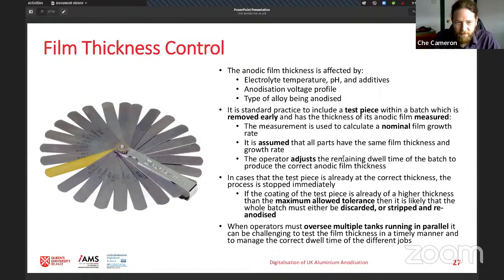There are a few issues with the assumptions there, that you're assuming the process is the same on all the different parts and all the different types of parts, but this is how it's generally done, and it's reasonably reliable. There are cases that when you remove that test piece, the anodization is already at the correct thickness, in which case you stop the process immediately. But it's also not uncommon that you remove that piece and you see that the film is too thick already for a geometrically accurate part that may be beyond tolerance now. So you either end up discarding the whole batch or you strip and re-anodize it if that is feasible for the part. And the reason that this can be an issue is an operator may be overseeing multiple tanks running different type of parts at the same time, and it can be hard for them to get these test pieces removed, measured, the dwell times calculated properly, and make sure everything happens on time.